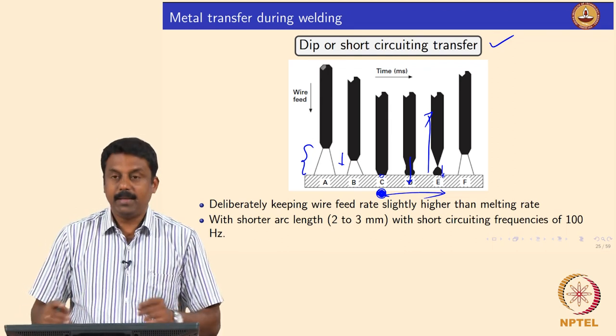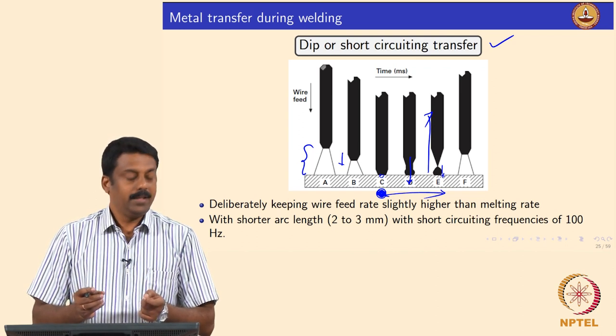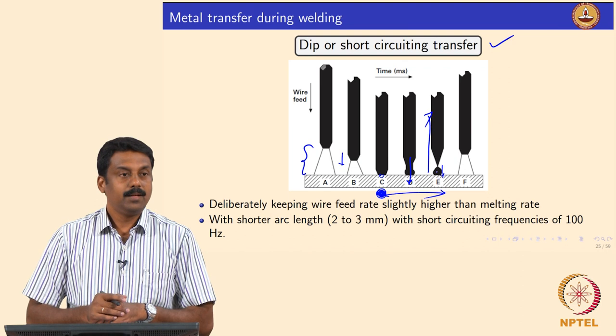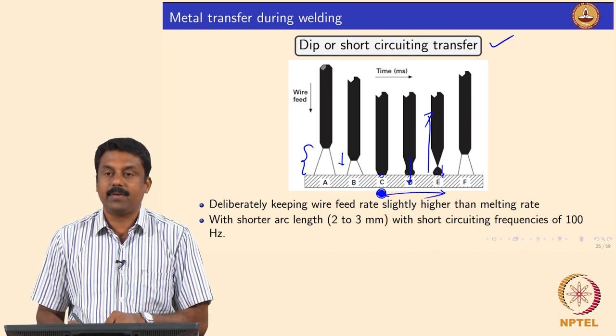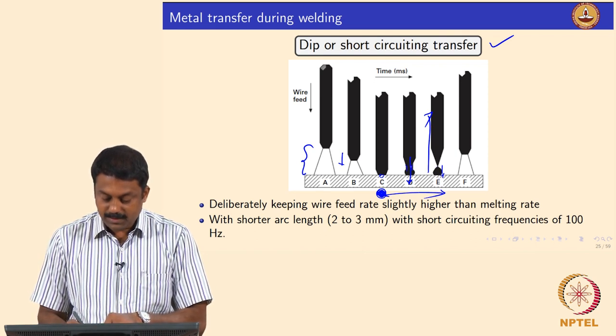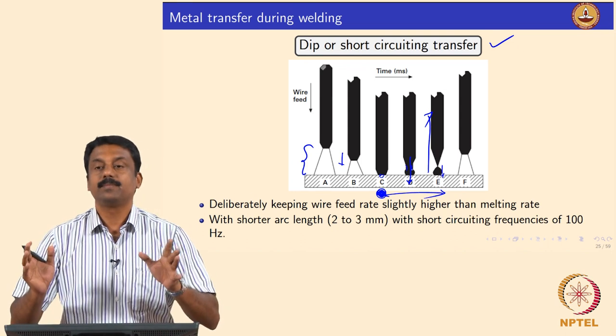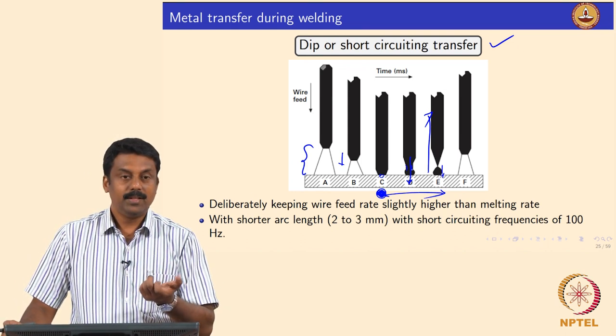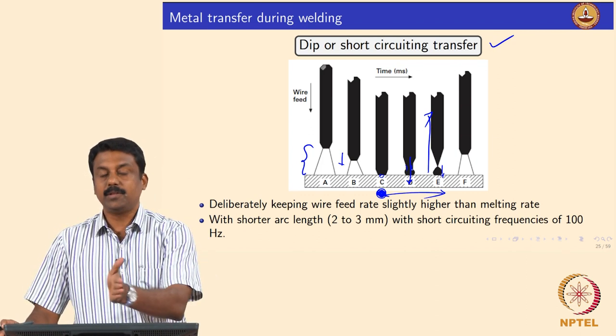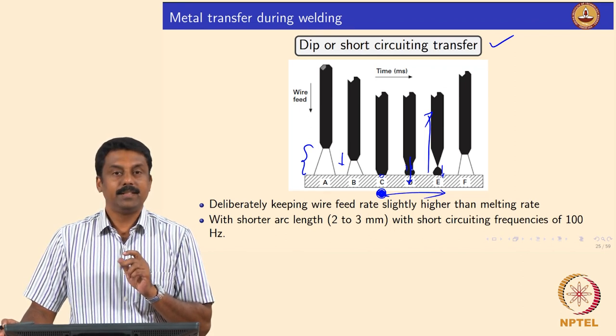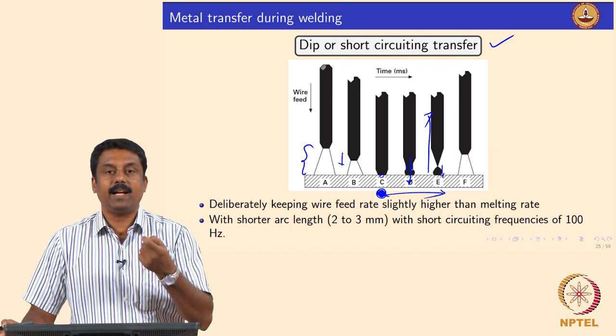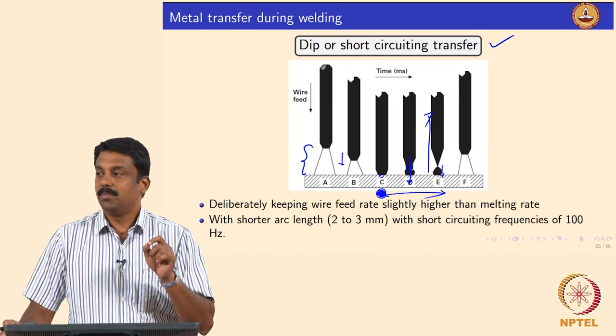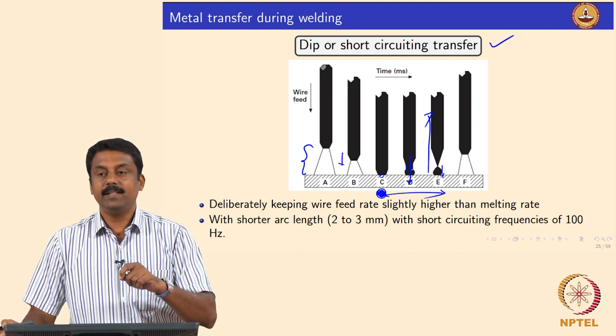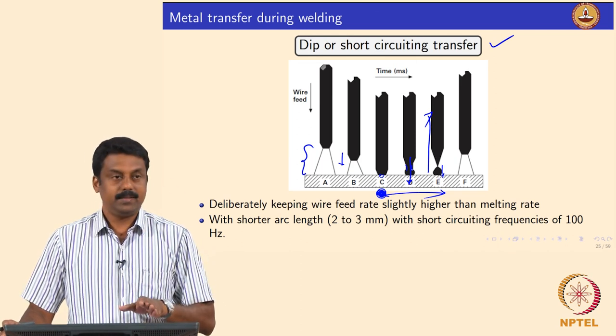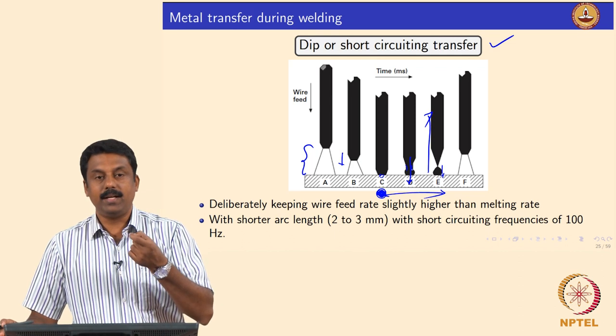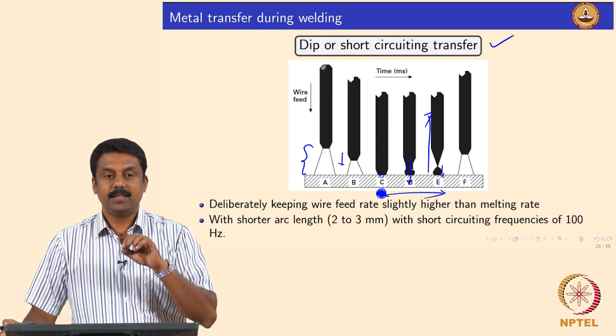During this process, by carefully manipulating the current voltage waveform, we can transfer the droplet without any explosion. That is very critical, because if you keep on passing the same amount of current when you form a neck, then the Lorentz force becomes so high that you will have an explosion. So, your power source should be capable of turning the current off the moment short circuiting happens. By deliberately keeping the wire feed slightly higher than the melting rate, we can establish short circuiting. The moment short circuiting is established, we have to identify that moment and then switch off or reduce the current. And then the molten droplet at the tip can be transferred to the workpiece by the surface tension of the liquid pool.